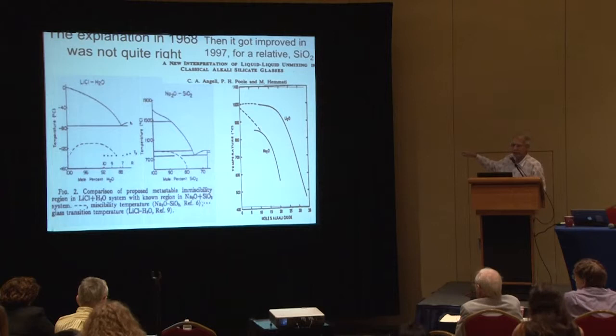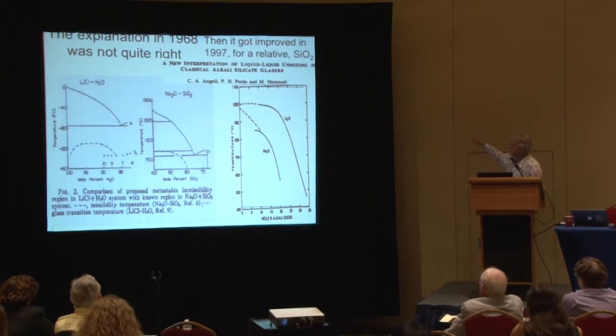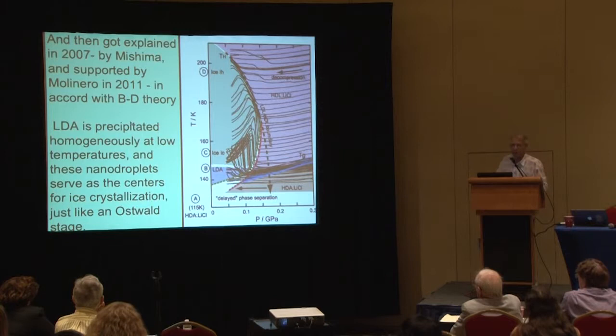It's because of the polyamorphism of water, and we've corrected it in '97 for the case of silica. Now Mishima, nicely supported by the work that Valeria showed you this morning, has defined this for us for lithium chloride solutions which were vitrified at modest pressures and then examined during warm-up.